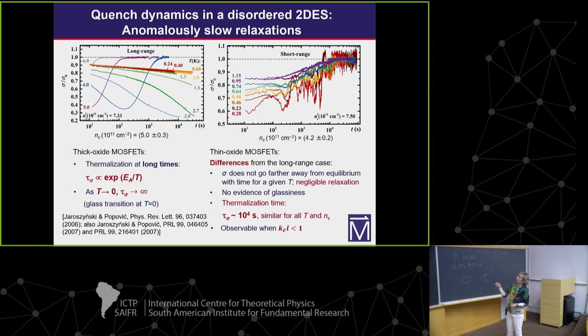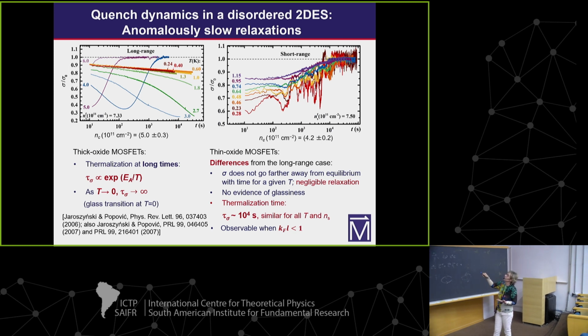Notably, initially at intermediate times, there is negligible relaxation. We have noise, but there is negligible relaxation. We do not see any evidence here of glassing. It's like we could fit this to a power law or stretched exponential.